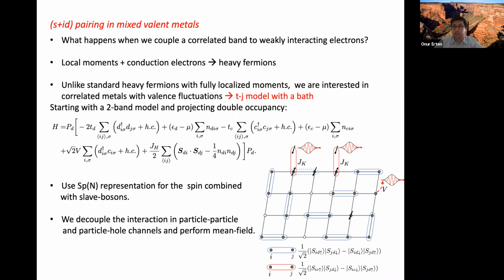You can have attractive interaction, and if your Fermi surfaces are such that they do not really overlap with the extended S-wave nodes, you will energetically be okay with picking extended S-wave. Actually, in the single band Hubbard model, the extended S-wave is not so far away from D wave and becomes favorable upon high doping, which is not really observed because at that limit, the TJ model approximation breaks down. It should only work near half filling. But in principle, if you take this approximation and go all the way to very high dopings, the extended S wave actually becomes lower in energy than D wave.